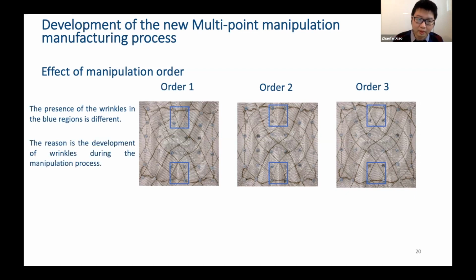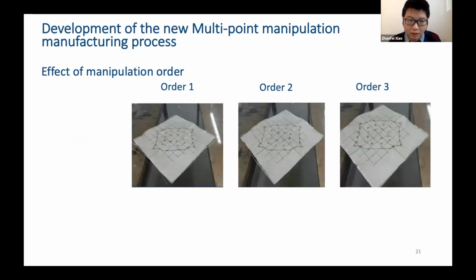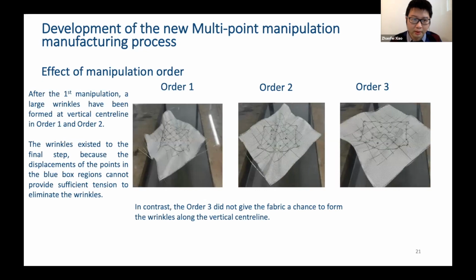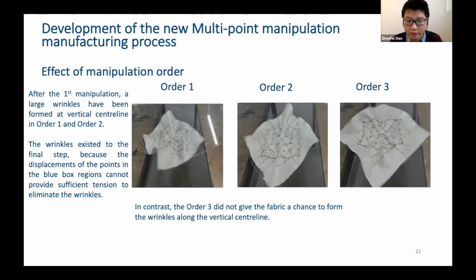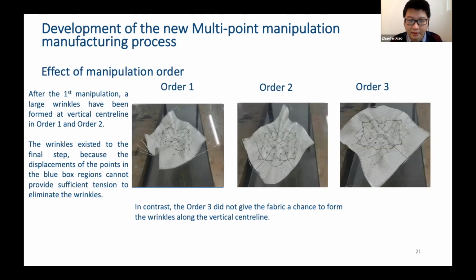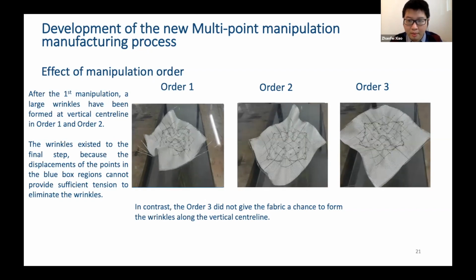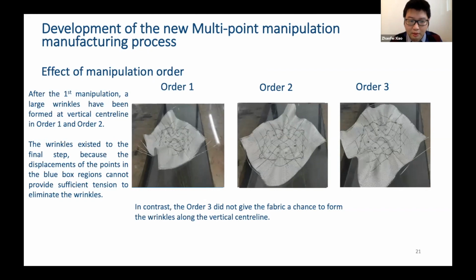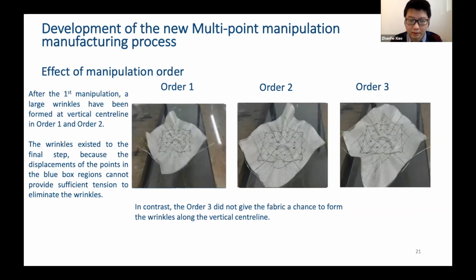The reason could be the development of the wrinkles during the manipulation process. So please let me explain. If we go through the manipulation process, after we finish the first manipulation, in order 1 and order 2, we can already see large-scale wrinkles along the vertical center line, whereas order 3 doesn't have that kind of large wrinkle. And these large wrinkles still exist in order 1 and order 2 until the final step, but order 3 doesn't give a chance to form the wrinkle along the vertical center line.